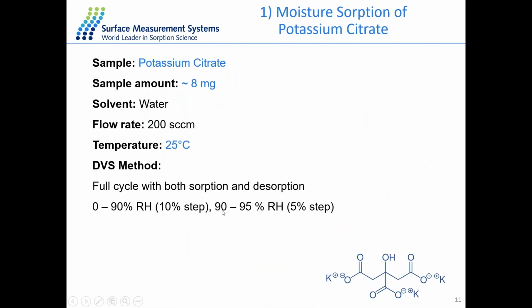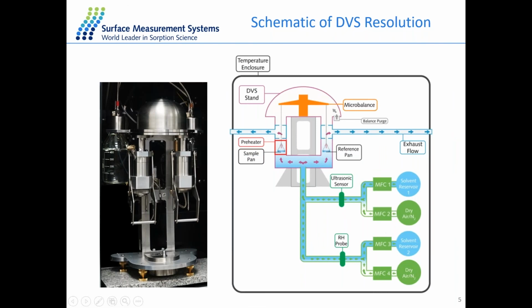Okay, that's great. We showed the instrument before. You can see here that there is a brass top on the top of the sample chamber, and that's the port for the Raman probe. You just put the Raman probe inside, and the software will automatically trigger the collection of the Raman spectra at the end of each humidity step. We do have the software already integrated with the Raman software. But if you have your own Raman spectrometer, you can also do it manually as well. And aside from the Raman, we can also integrate it with an IR spectrometer. As long as the sample is Raman active, we can perform Raman with the DVS.